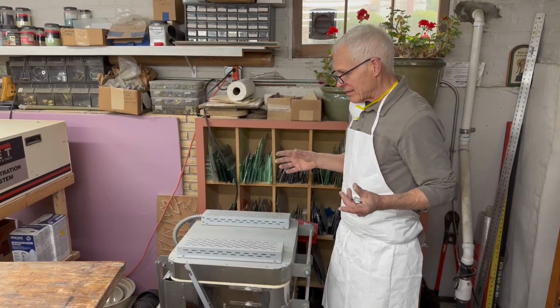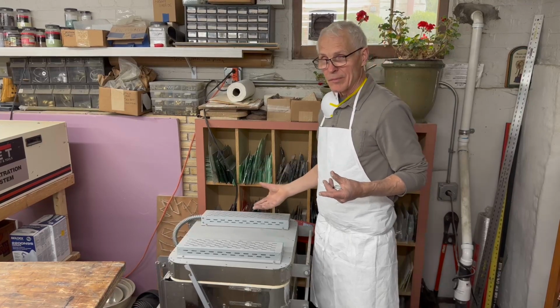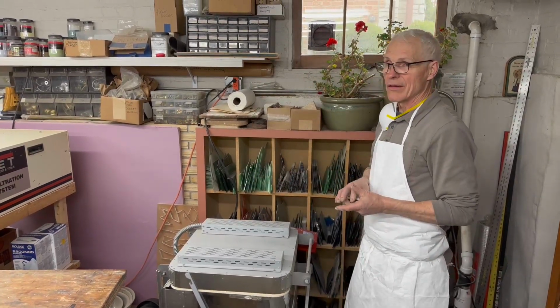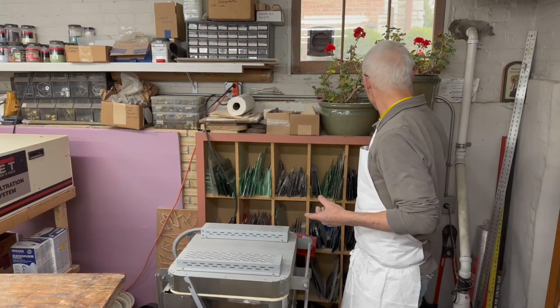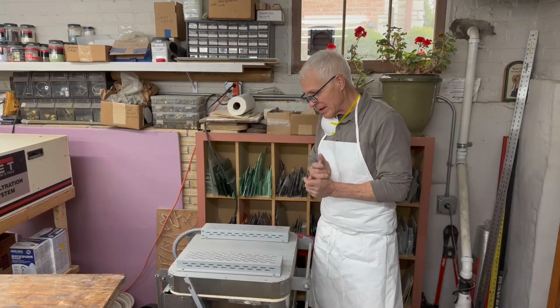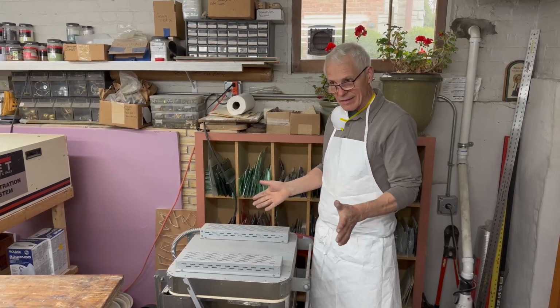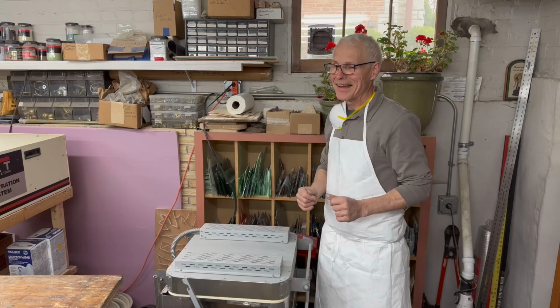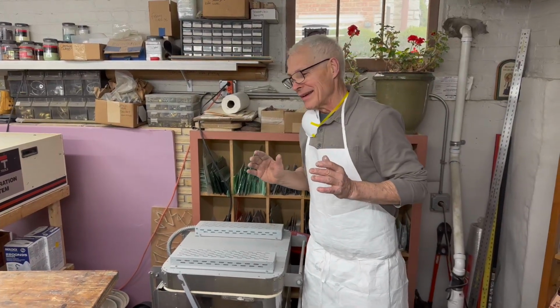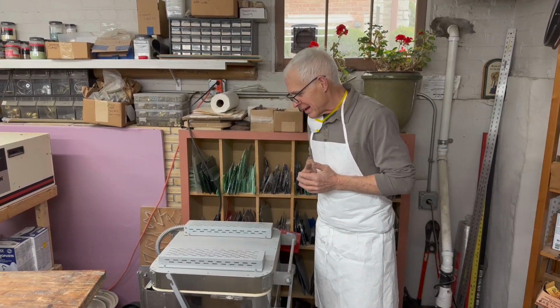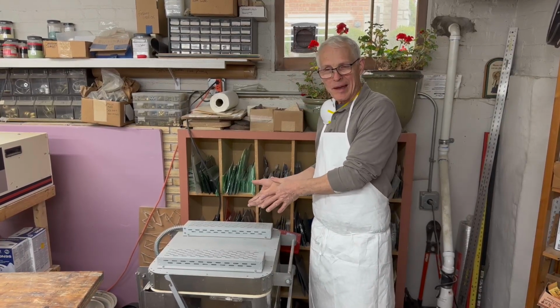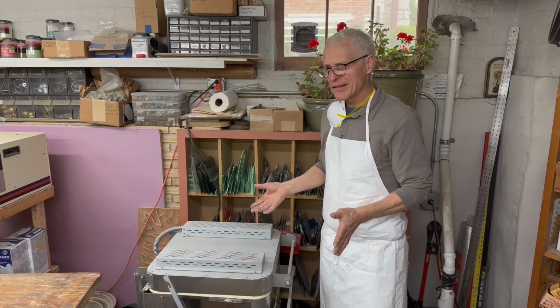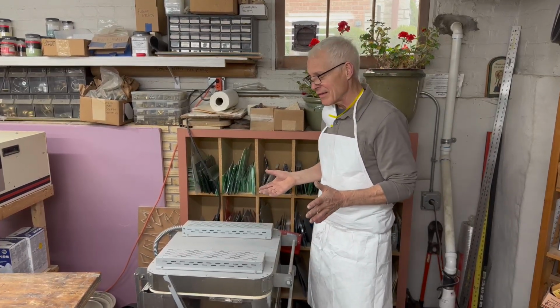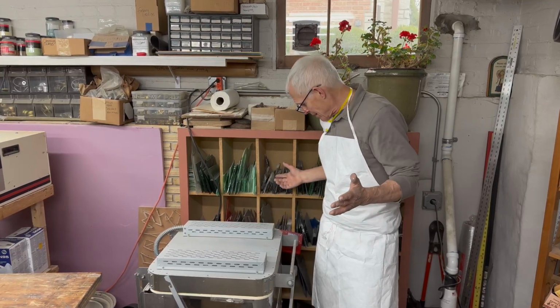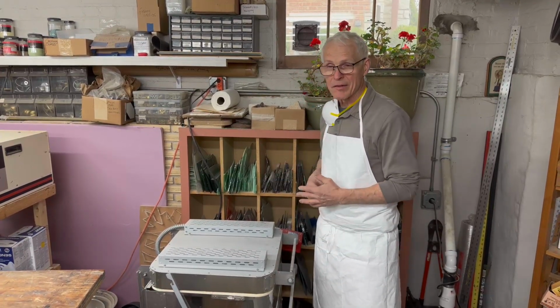A lot of folks think that you have to anneal it. We could put an annealing stage in for an hour or so. That's not a bad thing. But years ago, when they bent panels like this, they did them with torches and they just put the glass in a box with some asbestos and called it a day. Out of the 50 or so years of bending these panels, I've never had one come back cracked. So whatever I'm doing, I think it's working. Got the program ready, and we'll see how it goes.